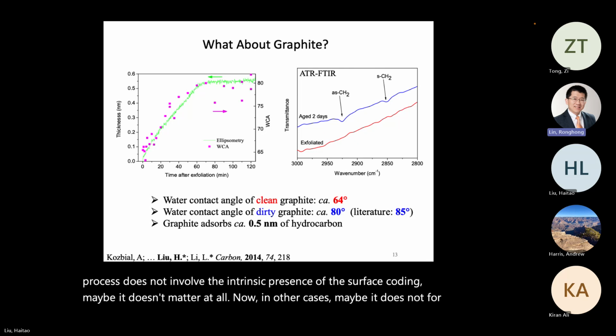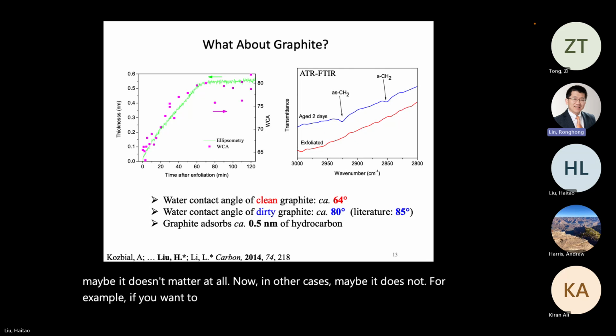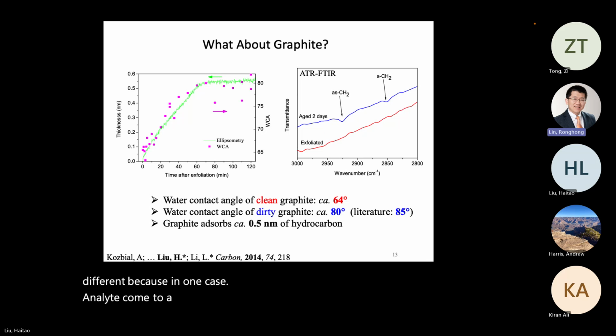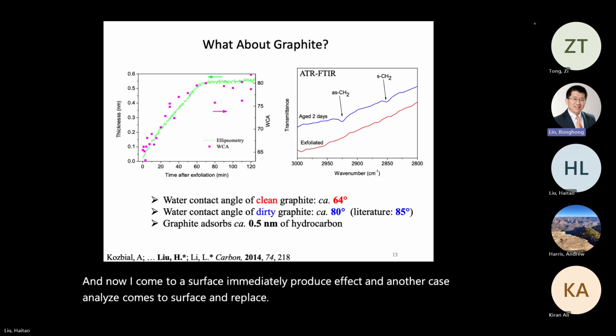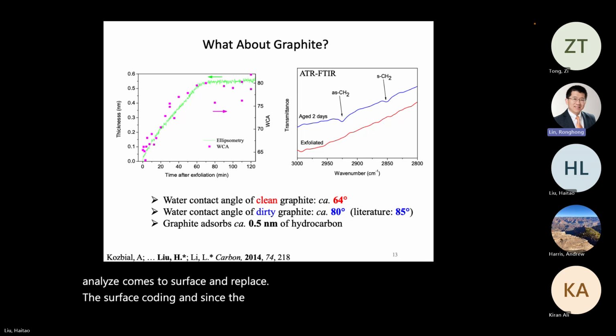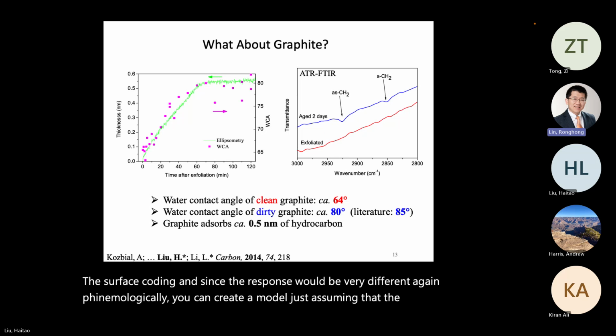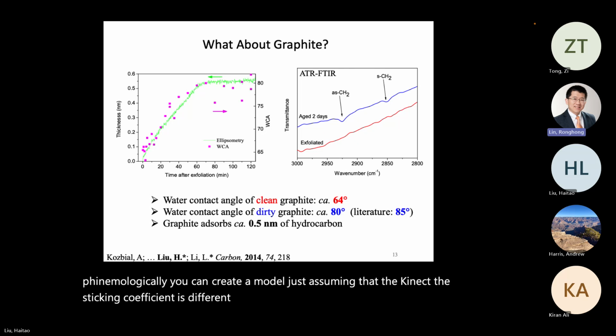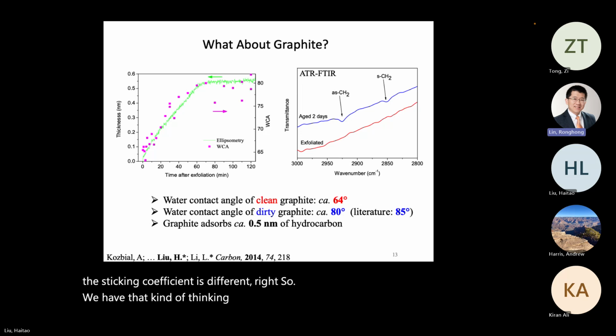For example, if you want to understand the sensing response of a carbon-based sensor, having that coating and not having that coating would be different, because in one case, the analyte comes to a surface and immediately produces the effect, and in another case, the analyte comes to a surface and replaces the surface coating, and the sensor response would be very different. Again, phenomenologically, you can create a model just assuming that the sticking coefficient is different, right? So if we have that kind of thinking, the party goes on, and I don't see a big problem.